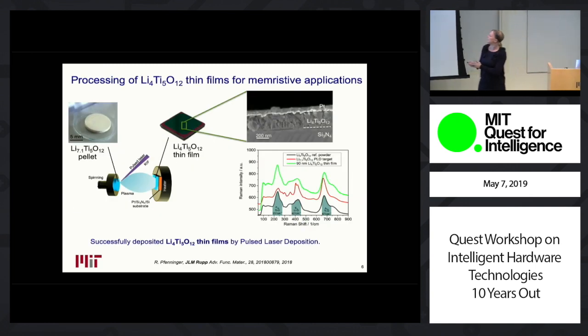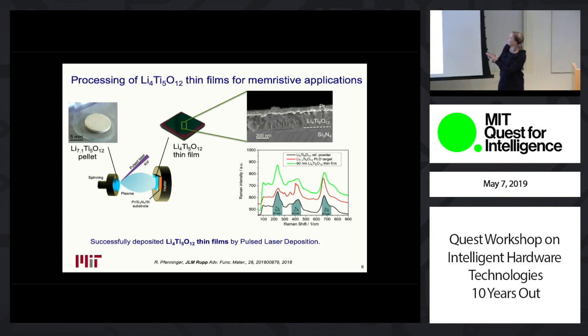What we have done is we have processed some lithium titanate thin films, and you can see an example made by pulsed laser deposition. It's a technique where we use a ceramic pellet, we ablate it, we shoot it with a laser, we love doing that, and then we deposit it onto a substrate, and you can create nice thin films. And here is a corresponding Raman spectrum showing that we have the phase.